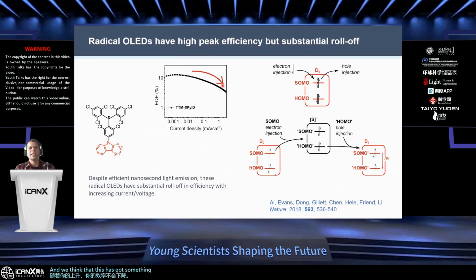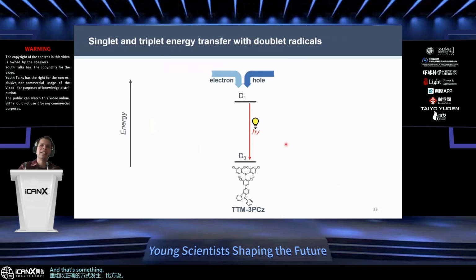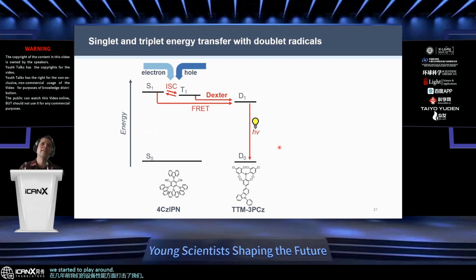And we think that this has something to do with a different nature of charge recombination in how these devices work. Whereas the singly occupied molecular orbital sets up a useful manifold of doublet excited states for your radiative transition, it also introduces a problem in which electrons and holes can also recombine at this state. So something that you have to do is to engineer your devices to make electron and hole recombination happen in the right way, let's say. And that's something that hit us in terms of the performance of our devices. A few years ago, we started to play around with energy transfer devices in which we took the charge recombination event away from the radical, which was posing some problems for us.